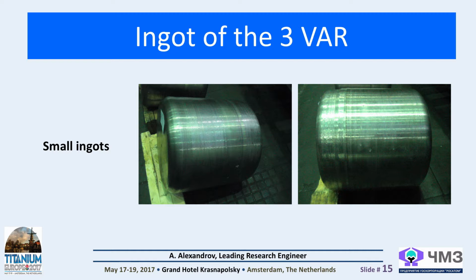The specificity of intermetallic ingots is high hardness. Therefore, turning takes much time and leads to increased consumption of cutters in comparison with ingots of widely used titanium alloys. So it's a rather great problem for us, and we are looking for actual instruments for this operation. The resulting roughness was 12 to 47 microns, when the requirement is no more than 50.